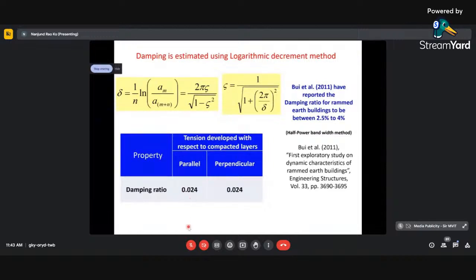And this result, which we tried to compare with the literature. There's a Bui et al. 2011, this is the paper. They also reported a damping of 2.5 to 4%, which was essentially for the unstabilized rammed earth. This is the logarithmic decrement method that we adopted.